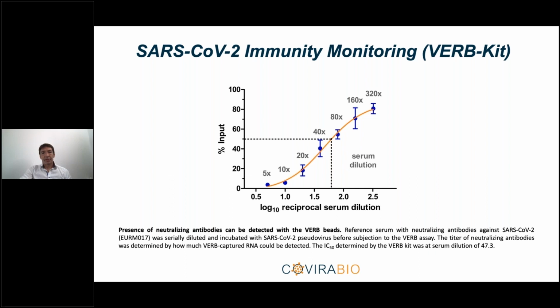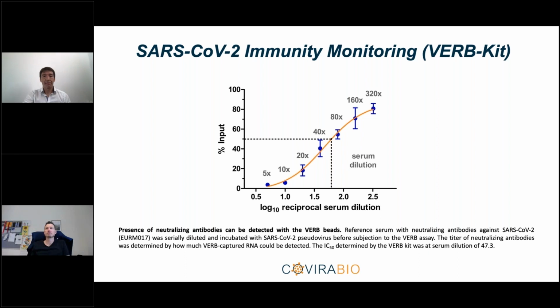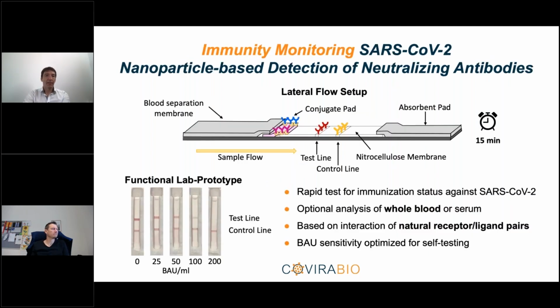So this is an example of the data that we received from immunity monitoring experiments, where we used reference sera for SARS-CoV-2 after immunization, of course, and we diluted this reference sera containing neutralizing antibodies in the verb-based immunity monitoring kit. And as you can see, you can get a very nice dose response curve here for detection of your neutralizing antibodies in your sample, and this principle is then applied to nanoparticle-based detection in the form of lateral flow setups.